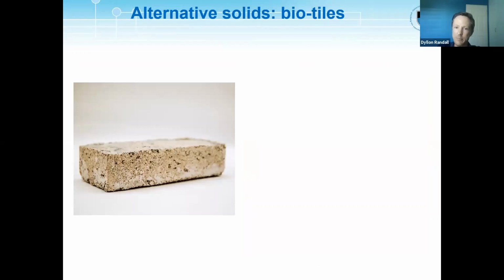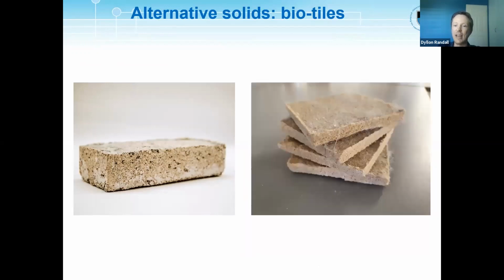So what does this actually mean for making biosolids? We've actually abandoned the production of biobricks, and now we're looking at thinner material simply because of this issue with the diffusion of oxygen and nutrients. The thinking is, if we can make thinner materials such as bio-tiles, we overcome these challenges, because we can have a very thin material using essentially the same volume of aggregate, but not have to worry about not having a solid material in the interior, such as the brick or the column.